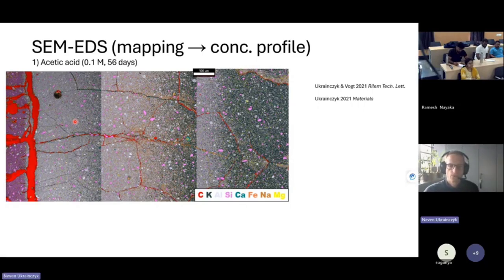There is like under vacuum. It's a typical preparation method for SEM when you want to preserve the microstructure. So you should dry the sample, but not too much, typically 40 degrees, maximum 50 degrees drying, and then put it under vacuum machine, and then add epoxy, because that sucks the low viscosity epoxy into the pores, and then harden the epoxy, and then polish the sample.